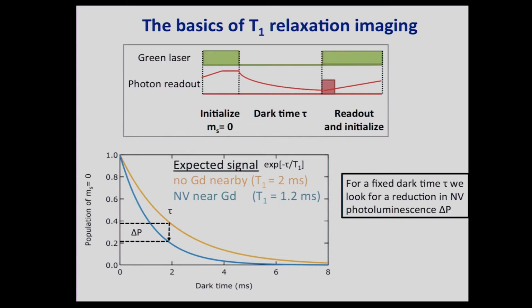And these two levels, remember, have a different level of fluorescence. So we initialize our system into one spin level. It becomes bright, and then we turn off our laser. And then in the absence of any light being shined on the NV center, it will slowly relax to its equilibrium state, which is some mixed state between these two levels. And it does that with a characteristic time scale, which is called the relaxation time.